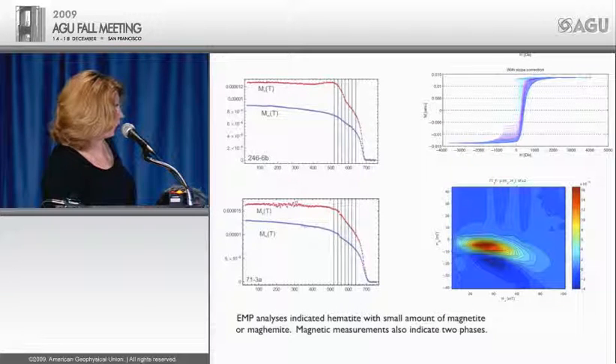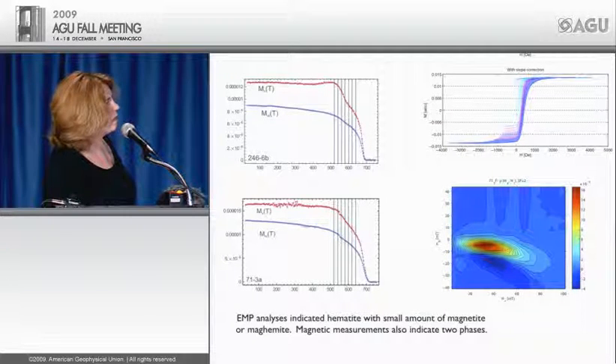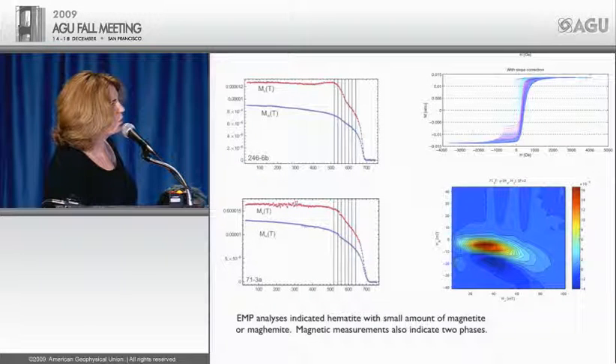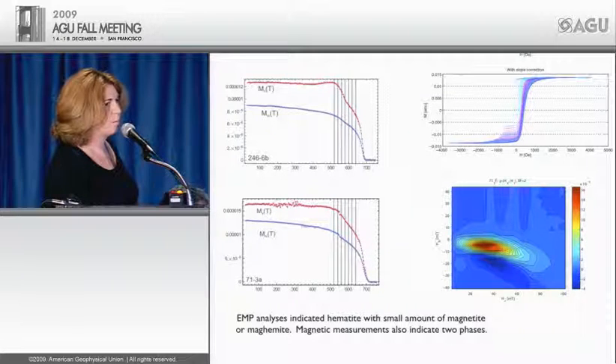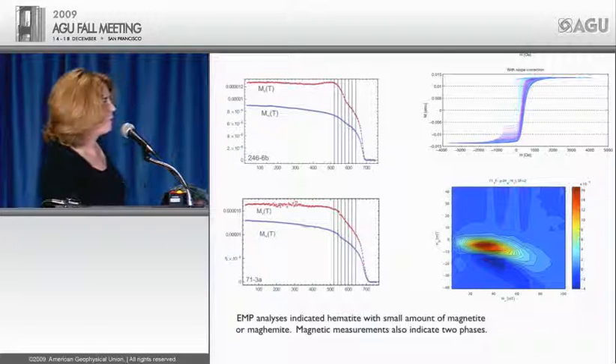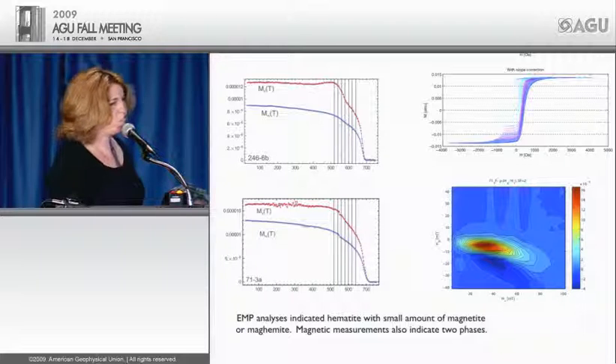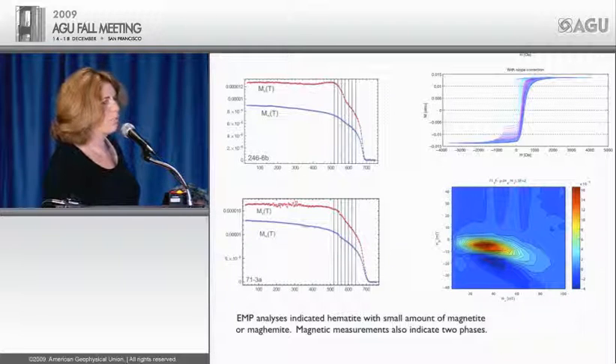And here, what we see are just some MS and MR curves, and you can clearly see there's more than one phase in them. And just on the right here, what we're looking at is a FORC diagram from the very low susceptibility, high remanence samples. And it certainly wouldn't be modeled as a multi-domain hematite. So we're trying to do more work on the TEM to look at what's the nature of these intergrowths that are in this material.